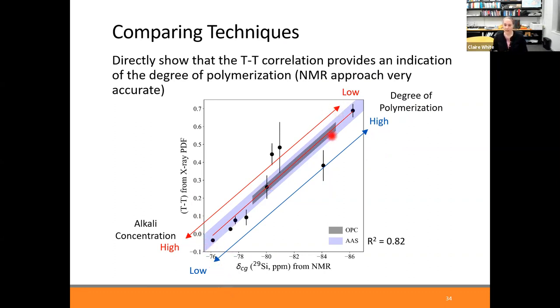What's shown here in gray is the span for the gels that tend to be in Portland cement concrete. And what's shown here in the purpley blue is the span that we have for the gels that exist in alkali-activated concrete. So it's important with the chemical composition of your system to choose it carefully, because it's nice to be in this region. We're going to have a more polymerized gel. It's likely going to be more stable compared to if we're down this end on the plot.